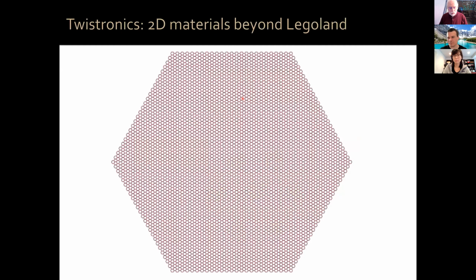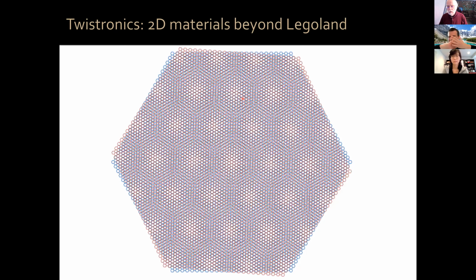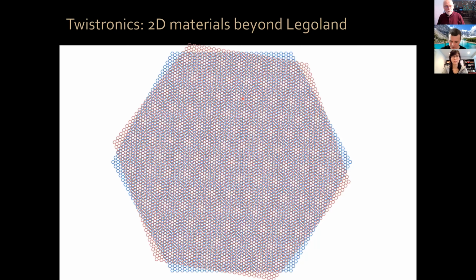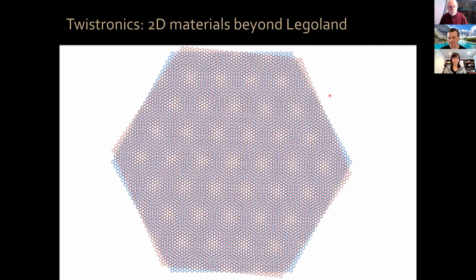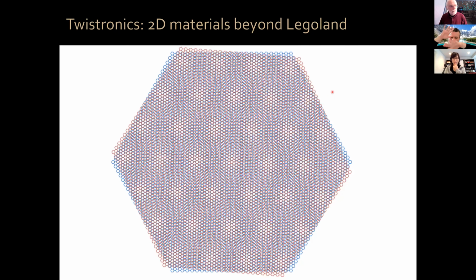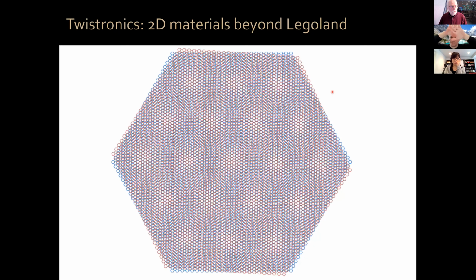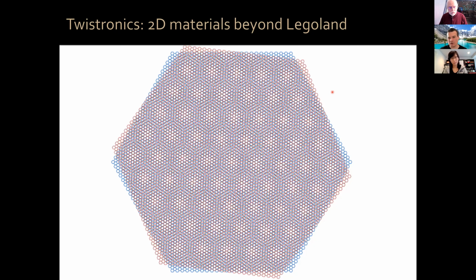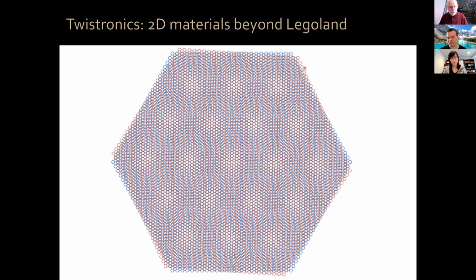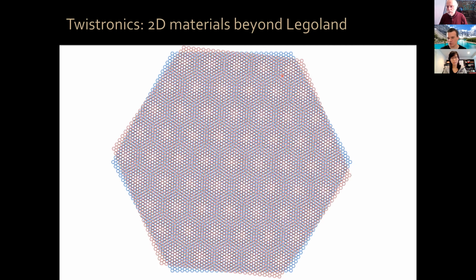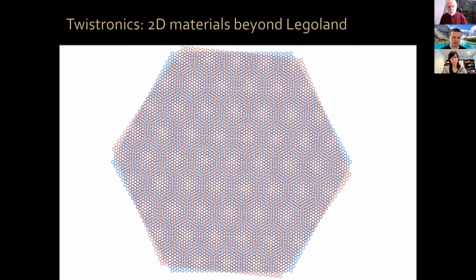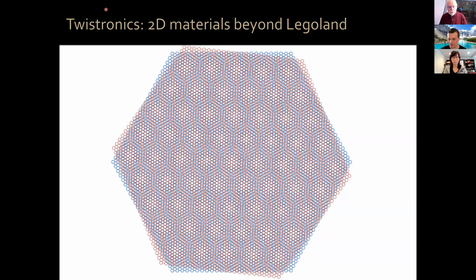Now, the thing that has made this Moiré quantum platform possible is something for which there was no precedent in the history of material science, which is the ability to vary the twist angle between two crystalline lattices completely at will. Okay, so with the advent of 2D materials, we were able to not only place them on top of each other, that already gave us a lot of freedom, but we were also able to put two 2D crystalline lattices at any angle that we choose on top of each other. Okay, and that is a knob, that twisting, which sometimes people refer to as twistronics. That's a knob that was not present earlier.